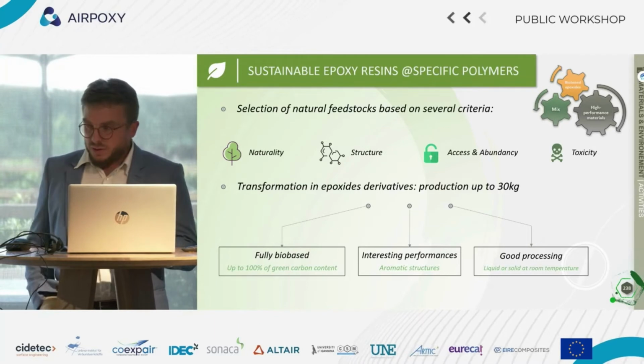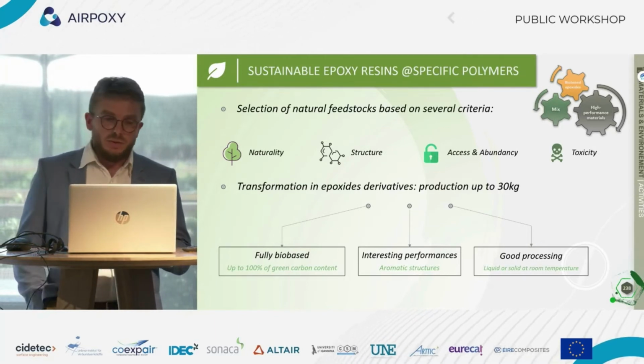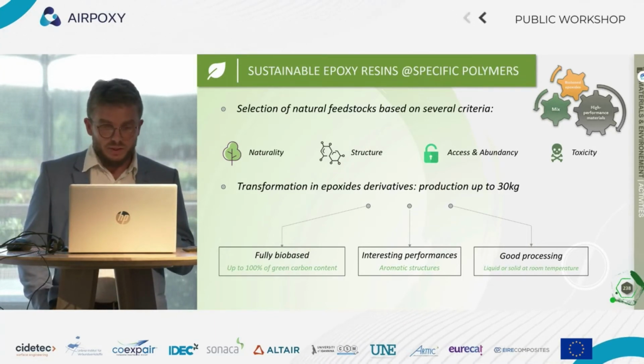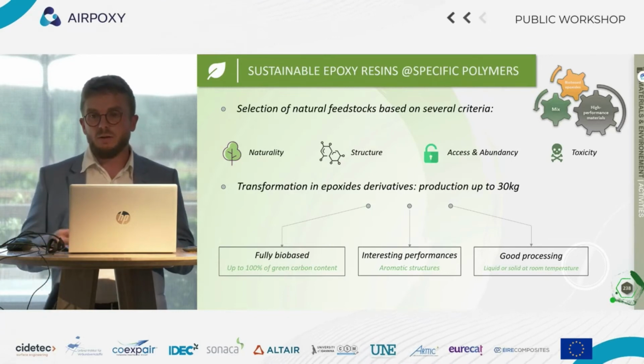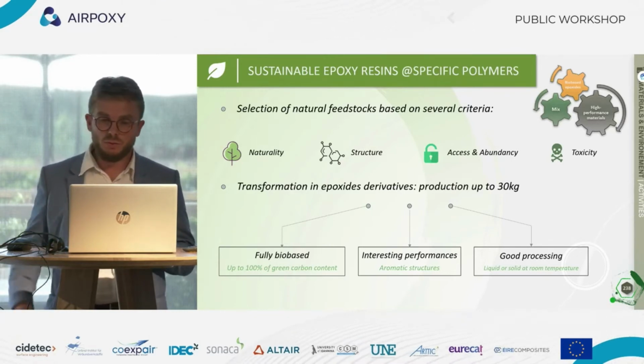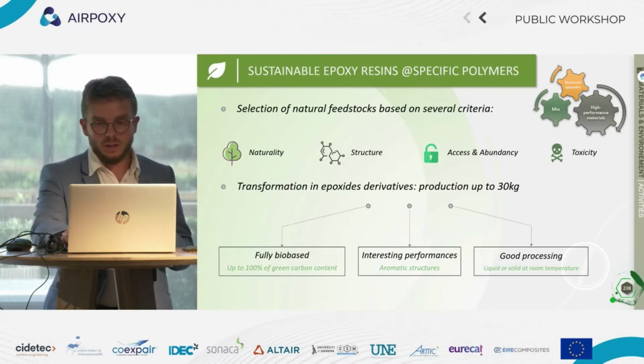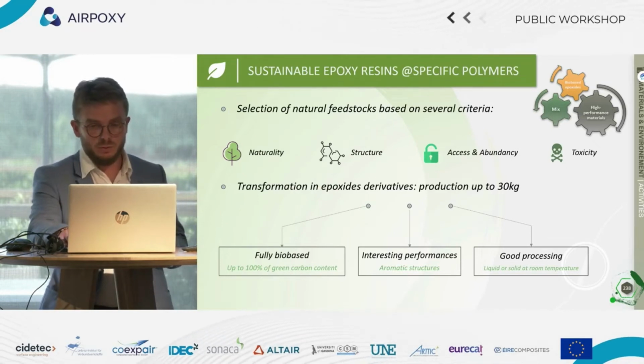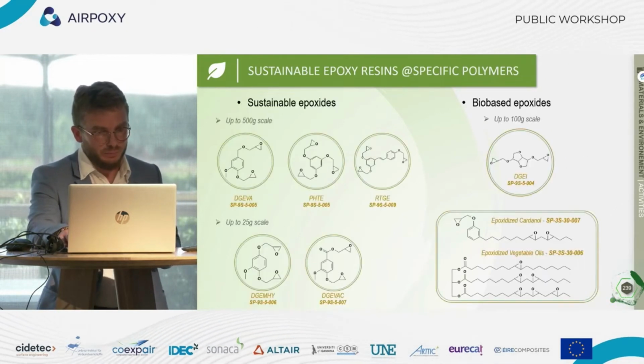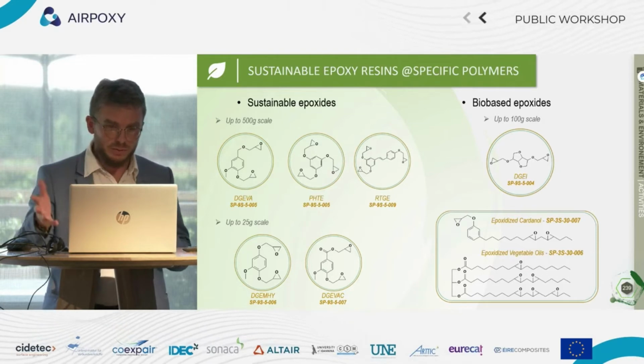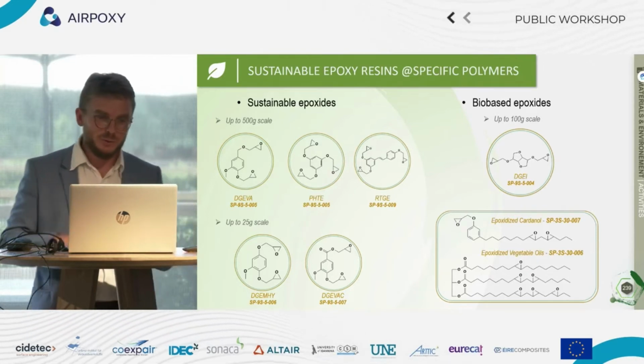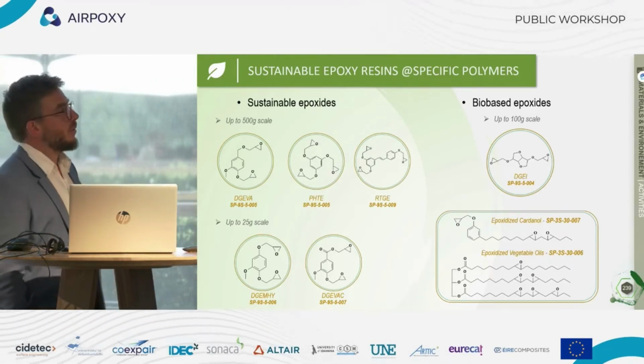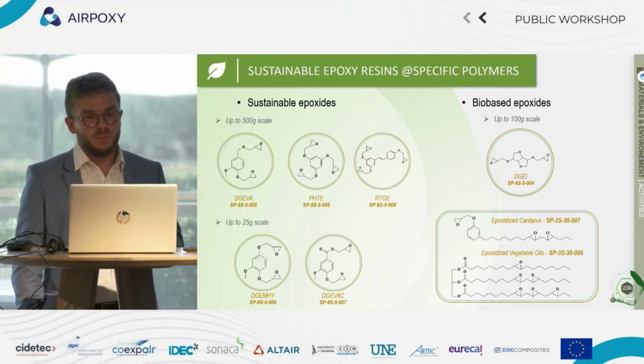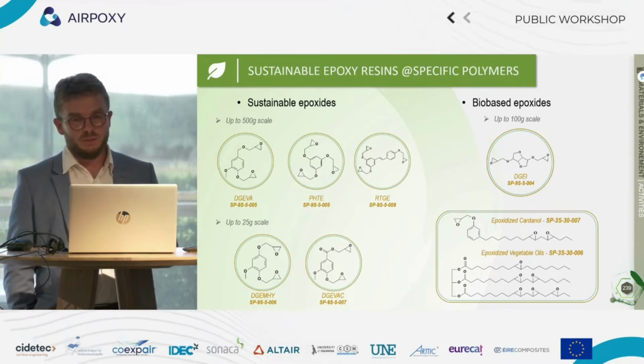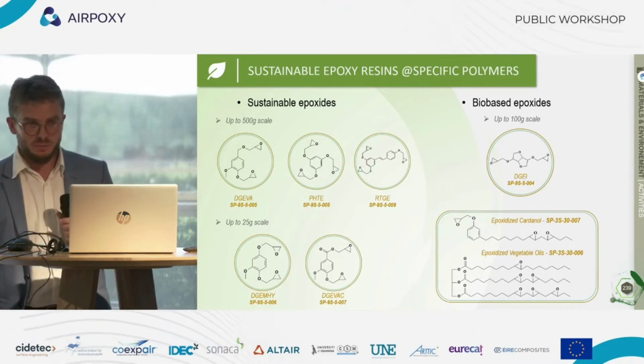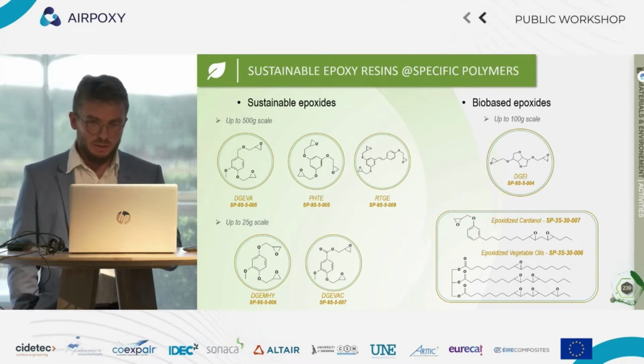And then when we have identified the precursors, the objective is to convert them into epoxies and, time by time, go to a production of at least 30 kilograms in order to achieve some tests. So this is some chemistry. I'm sorry, but I need to show the chemistry of the main precursors we developed in the past, and we made a differentiation between sustainable epoxide and bio-based epoxide.